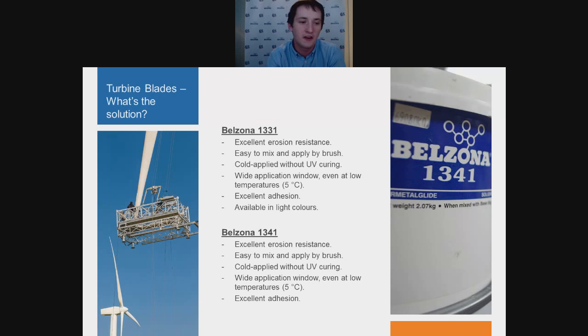So when you're looking for leading edge protection, you're looking for two things. First of all, performance. Does it stop the erosion? So both of these materials have been through extensive in-house testing, but also external erosion testing. So this also includes the ASTM G73 rain erosion test. In addition to this, we've got a lot of case histories and examples where we've used these materials in very erosive environments. So things such as cooling tower fan blades and high velocity pumps. But we also have examples as well where these have been used in the wind industry on blades.